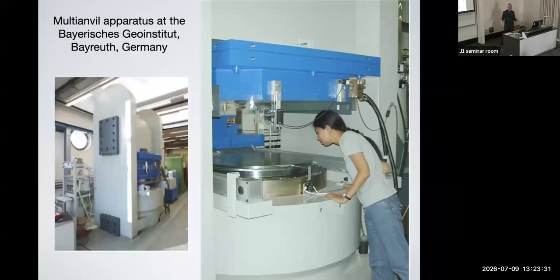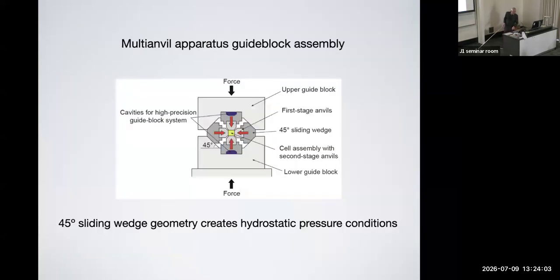So this machine, to my knowledge, there are 3 of these. 2 of these are on a synchrotron, which doesn't do you any good for grain growth experiments because you don't monitor and you don't need to monitor them in situ. Plus, usually on the synchrotron, you get only hours or a day or so. And we did lots of experiments that ranged up to a day in runtime. So we couldn't have done that study on a synchrotron. So this one is not on a synchrotron, and hence that's pretty much the only place where you can do these experiments at that pressure.